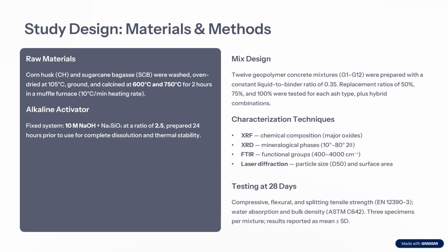For raw materials, corn husk, abbreviated here as CH, and sugarcane bagasse were washed, oven dried at 105 centigrade, ground, and calcined at 600 centigrade and 750 centigrade for 2 hours in a muffle furnace at 10 centigrade per minute. For the alkaline activator, we use 10 molar NaOH plus Na2SiO3 at a ratio of 2.5, prepared 24 hours prior to use for complete dissolution and thermal stability.